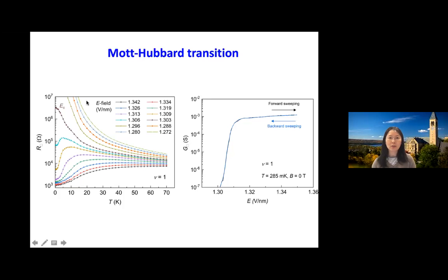For this group, when you lower the temperature, the resistance goes up monotonically, and this is an insulating behavior. This one is a little bit special: throughout the temperature range, it follows a power law. Now when you look at the second group, when you lower the temperature, the resistance decreases, and this is a metallic behavior.